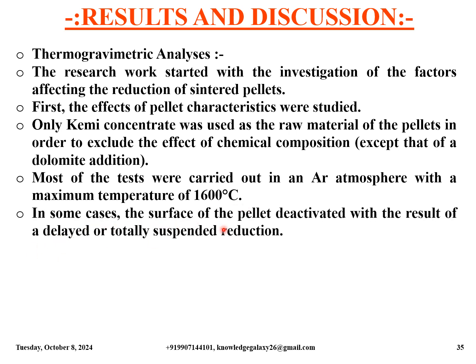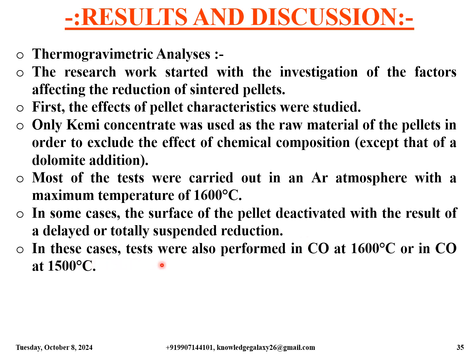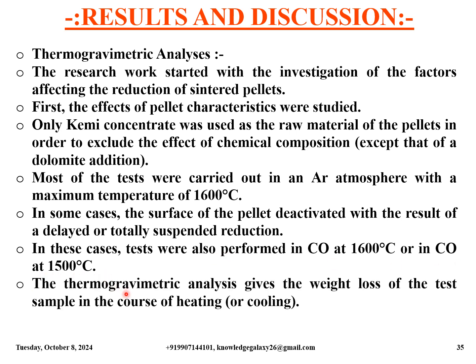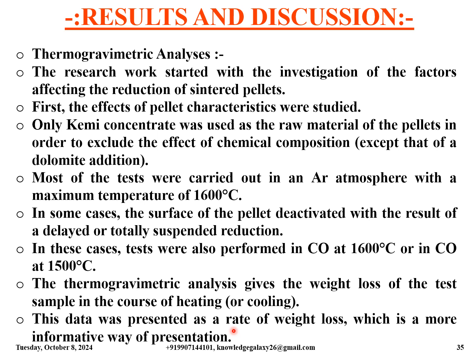Most of the tests were carried out in an argon atmosphere with a maximum temperature of 1600 degrees Celsius. In some cases, the surface of the pellet deactivated with the result of a delayed or totally suspended reduction. In these cases, tests were also performed in CO, that is carbon monoxide, at 1600 degrees Celsius or at 1500 degrees Celsius. The thermogravimetric analysis gives the weight loss of the test sample in the course of heating or cooling. This data was presented as a rate of weight loss, which is a more informative way of presentation.